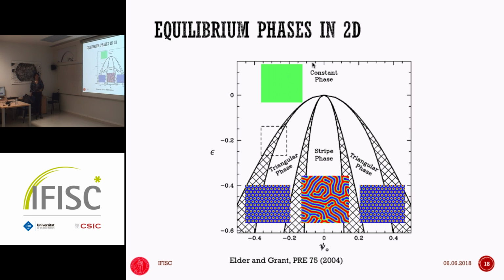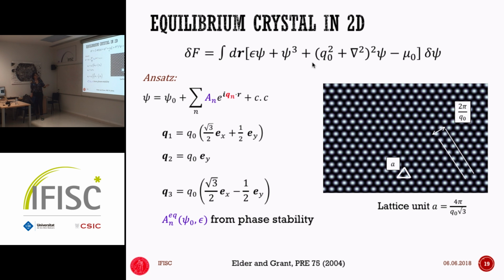All right? This has been the model proposed over a decade ago as a very nice phenomenological model for crystallization processes, anything related to liquid crystal phase transitions, and also crystal behavior. All right? But this is where it becomes phenomenological, because there is this step that you go from the correlation function to the gradient, and you have this gradient expansion. Everything else is supposed to be derived from this. So if you believe this phenomenological free energy, everything else comes as a consequence of this setup, right? So this is the level of: we have a phenomenological free energy, and then the rest follows from that.